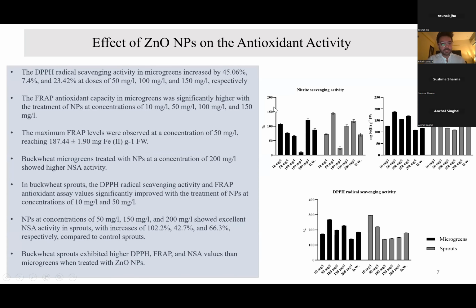Talking about the antioxidant activity, the effect of zinc oxide nanoparticles on the antioxidant activity, the DPPH radical scavenging activity increased at concentrations of 50, 100, and 150 mg per liter in microgreens. The FRAP antioxidant activity also increased with 10, 50, 100, and 150 mg per liter concentration. In buckwheat microgreens, the nitrite scavenging activity was increased by 200 mg per liter concentration. While talking about sprouts, the DPPH radical scavenging activity and FRAP antioxidant activity were increased at concentrations of 10 and 50 mg per liter. Buckwheat sprouts, basically they exhibited higher DPPH, FRAP, and nitrite scavenging activity as compared to microgreens.